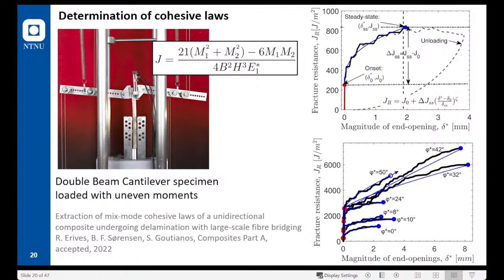When one develops an experimental technique, one should try to avoid errors. In most of the cases that you see in literature, the load is applied by forces. Here we apply moments. And when you apply moments, the J integral is independent of the crack length, so you don't need to measure the crack length, which can introduce a lot of errors when you calculate the J integral.